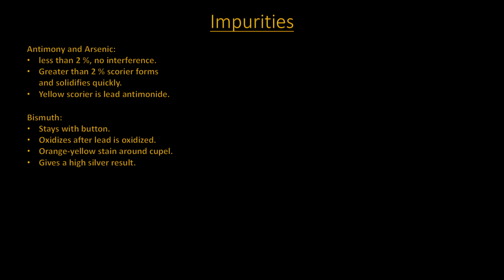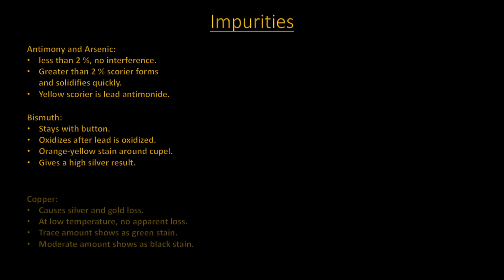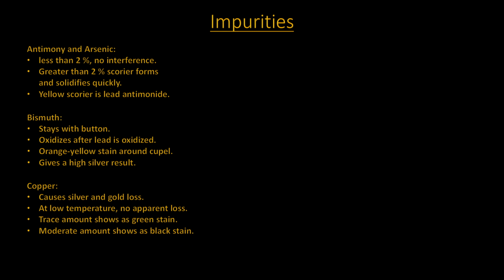Due to the longer cupellation time and an increase in cupel temperature due to the oxidation reaction, silver loss is increased, and so is some of the gold. After the cupellation is complete, there will be some bismuth left in the doré bead. After parting, a higher silver count will result. Copper, as with bismuth, will also oxidize after the lead is gone. This also adds to the losses due to absorption. The doré bead will also retain some copper.